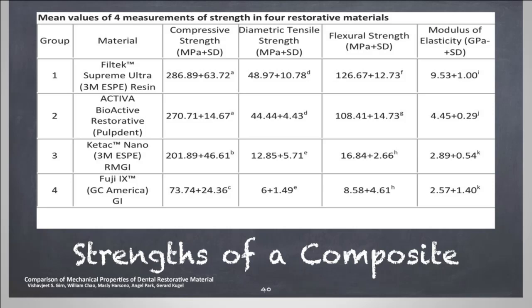Because what we're really trying to do with the rubberization of Activa is mimic the function of dentin, and that is the ability to absorb shock. The ability to absorb shock in our minds, especially for the company I work with, Pulpdent, is to protect the pulp. We like pulps. And that's why we like glass ionomers all these years, because it has a modulus that's very close to that of dentin and has done a very good job of protecting pulps as well. So you can see it's about half that of the composite materials, and we're very proud that we're reaching closer and closer to that of the natural function of tooth in the physical properties of these materials.